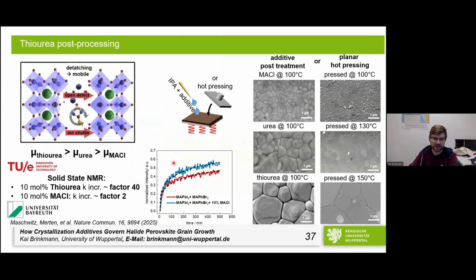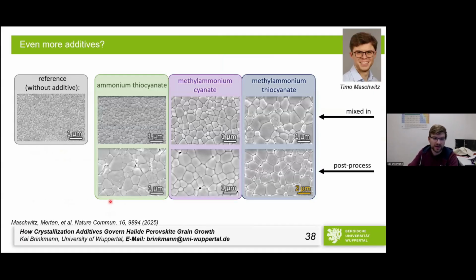We did the solid state measurement again and had a look at methyl ammonium chloride as another extreme. Unsurprisingly, we got exactly what we expected. So with thiourea, we got a factor of 40 in terms of mobility, while methyl ammonium chloride gave us a factor of 2. And actually, the easiest way to check if this works for other additives is to just spin coat them on top, and then put it on a hot plate. And yeah, surprise, surprise, ammonium thiocyanate, methylammonium cyanate, methylammonium thiocyanate all behave exactly the same. Everything else, we were not able to dissolve in something that does not hurt the perovskites. So these are the ones that we chose in the end. But I would actually guess if you are able to evaporate one of these others on top, you will get exactly the same results.